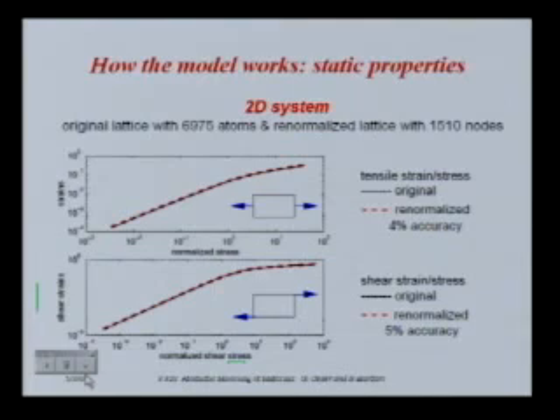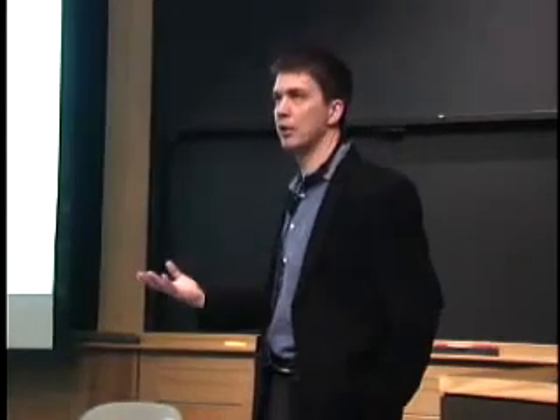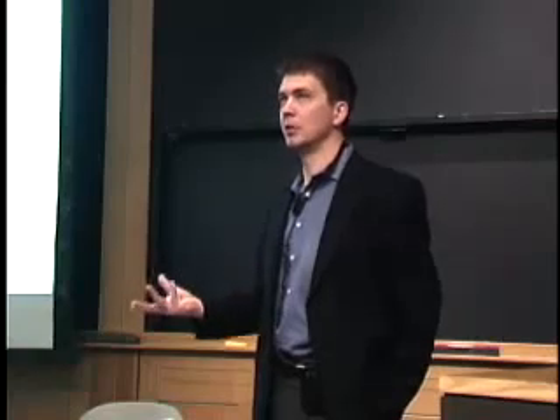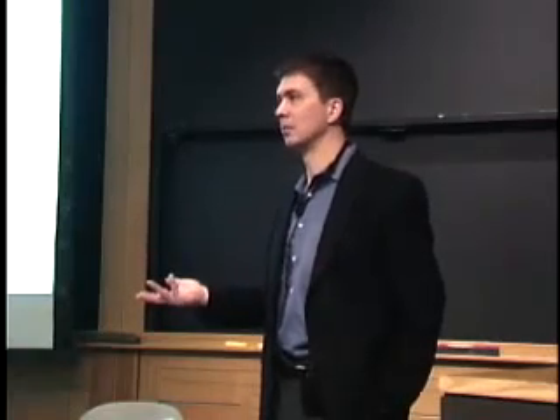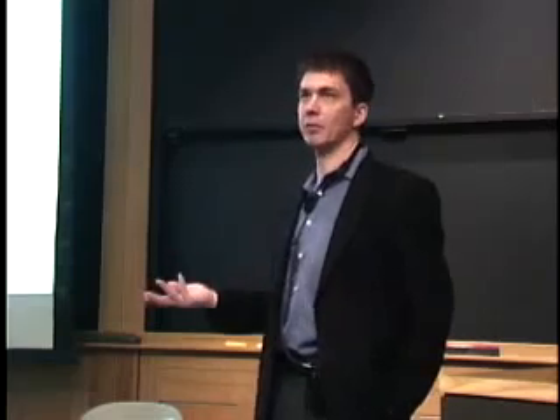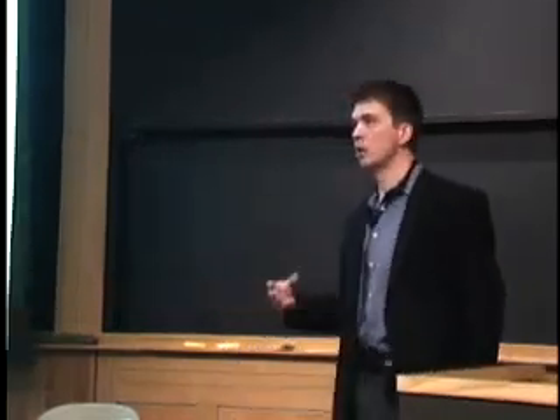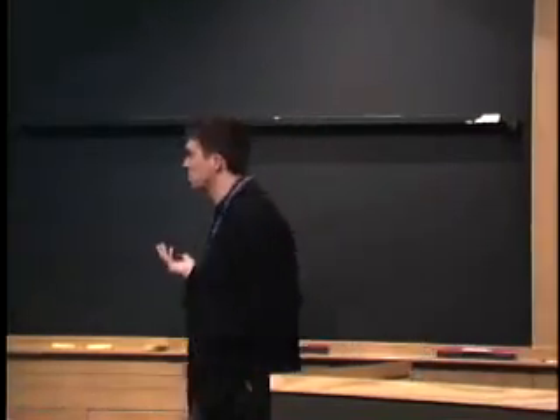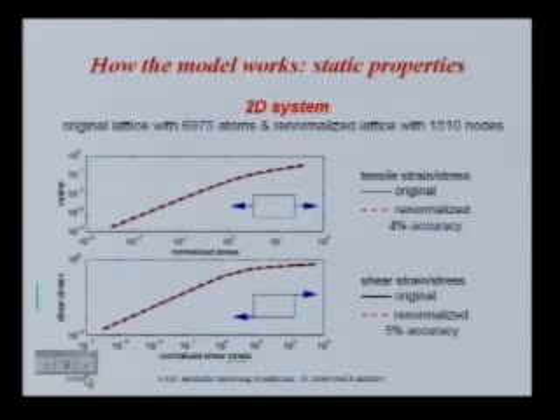You'll see, even in the nonlinear part, this does very well. And it makes sense—this kind of mechanical behavior, strain versus stress, is largely dominated by the potentials in these kinds of solid systems. There's very little dynamical factors that play a role in it. So as long as you normalize the potentials right, you will get the stress-strain relation right, even in the nonlinear regime. So that's not a big surprise.